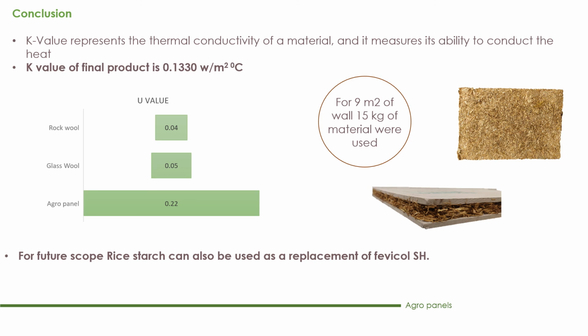After testing for thermal conductivity, the result obtained was 0.1330, heat flow per unit area per degree temperature difference. This value can be lowered if cement sheets are eliminated and replaced with a material which has lower thermal conductivity. For further scope, rice starch can also be used as a replacement for Fevicol as a natural binder.